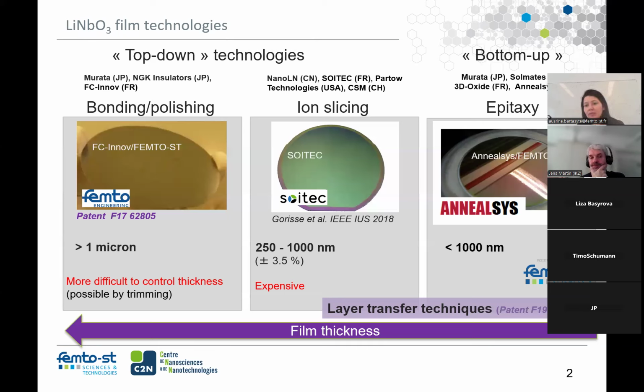And then the last method, which was abandoned, and of course it was very difficult to continue to compete with these single crystal films by growth. So that's why when these films came, everybody just abandoned the growth. Because when you grow the film, of course, it depends on the substrate. It's very difficult to get single crystal quality film. You are limited in what you are growing because you need epitaxy, so your substrate orientation. Then you can use sapphire, mainly sapphire substrates have been used. So we have a lot of limitations.